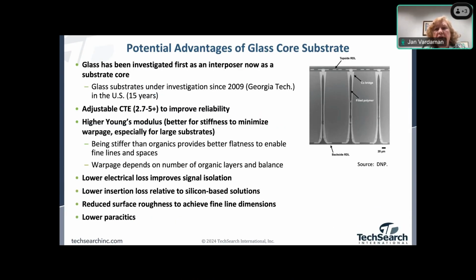So if we look at the potential advantages of a glass core substrate, glass was first investigated as an interposer back when we did all the research at Georgia Tech about 15 years ago in 2009. And we have the normal properties like adjustable CTE to improve reliability, higher Young's modulus for better stiffness to minimize warpage, lower electrical loss, lower insertion loss, reduced surface roughness, lower parasitics.